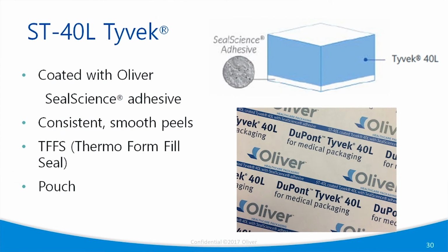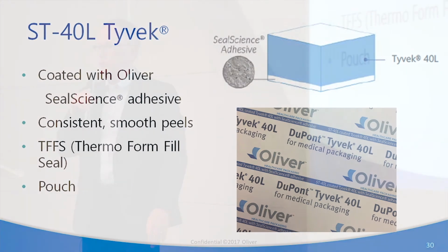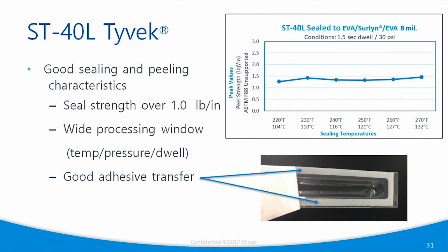40L, and at Oliver, we've coated this with a water-based coating, so our nomenclature is ST-40L Tyvek. So it's coated with our Seal Science adhesive, and really has nice, consistent, and smooth peels when we peel it off of various films. Works very well in a form-fill seal application. We've done a lot of testing in that regard, and it works very well. Also in pouch configuration, works well also. So as I said, very good sealing and peeling characteristics.